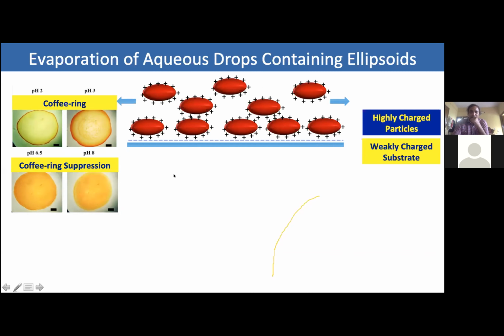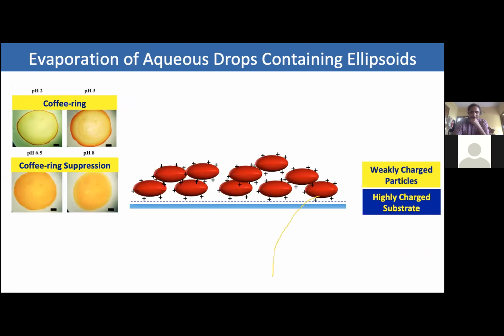Because the particle concentration is considerably higher, there could be some deposition of particles on the substrate, maybe a monolayer. But once this layer is formed, there's a repulsion between the ellipsoidal particles, and that leads to free particles in the fluid. These free, non-aggregated particles in the bulk are what are carried to the edge because of the capillary flow or the evaporative flows.